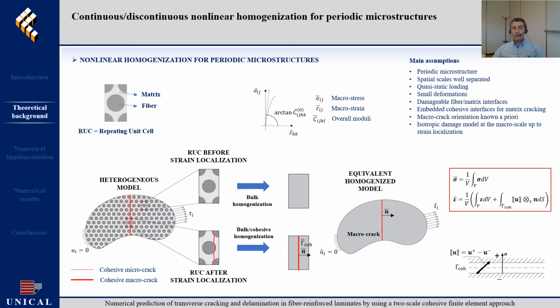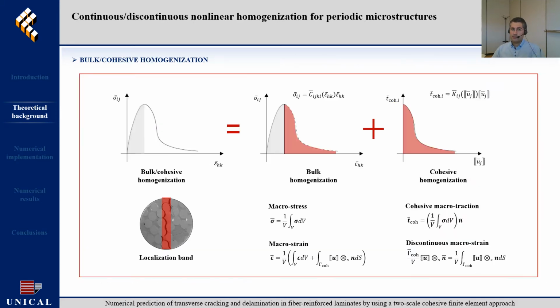Thus, also assuming periodic boundary conditions on the unit cell, a hierarchical homogenization scheme is applied with the aim of deriving the overall nonlinear response of the composite. To overcome the well-known ill-posedness of the homogenized macroscopic continuum problem in a softening regime, a further homogenization is performed at the interface level as a post-processing step.